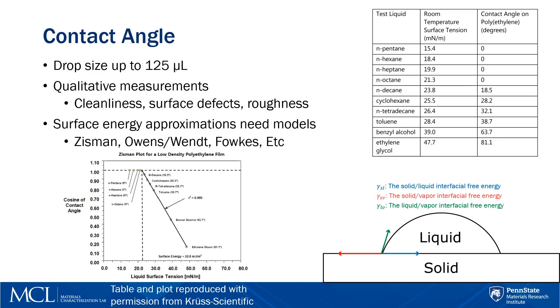If the goal is to approximate surface energy, however, a model representing the interfacial system must be used. The simplest model for this application is the Zisman model, which applies to surfaces that do not contain any polar contributions to the solid-liquid interface. A good example of a system that falls into this category are hydrocarbons on low-density polyethylene, shown in the table on the right.